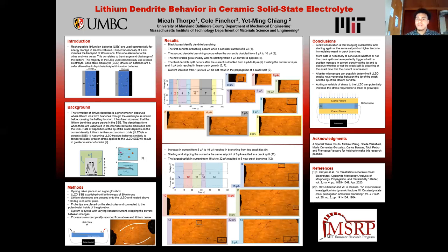As I alluded to before, lithium dendrites short the battery. When they grow directly across and short the battery, it heats up the battery and causes the battery to fail for liquid electrolytes. For solid electrolytes, the dendrites will crack the electrolyte and go across and reach the other side and short the battery very similarly. That's why this study is important, to understand how the cracks form and why they form and under what conditions they form and under what conditions they split.